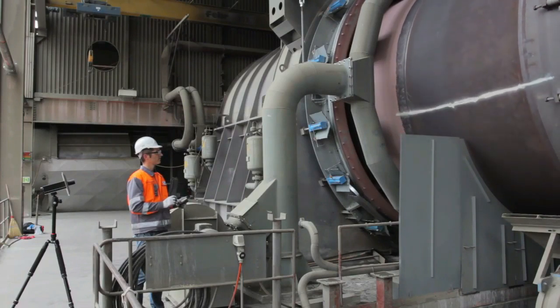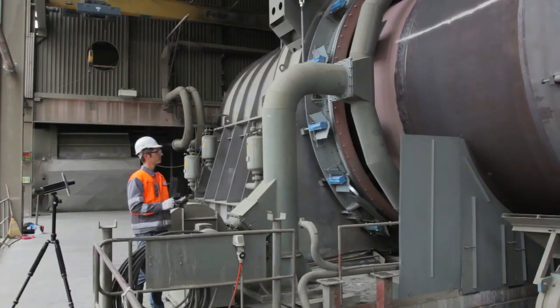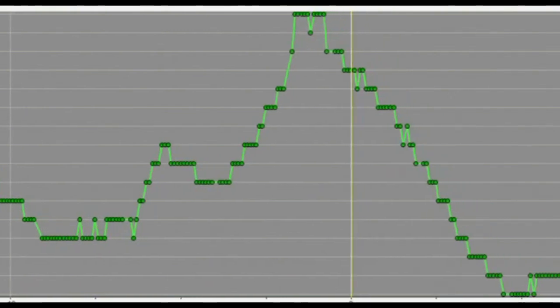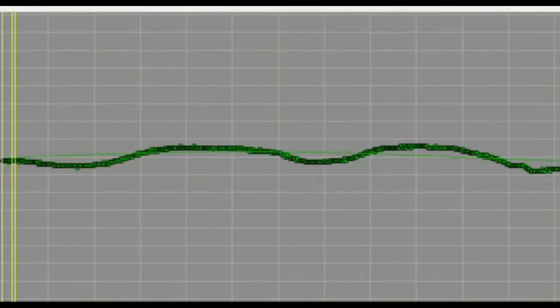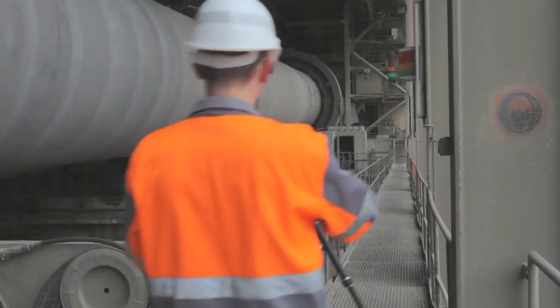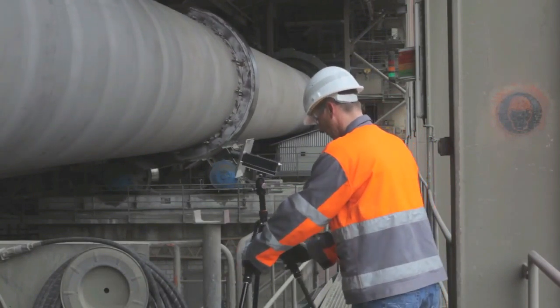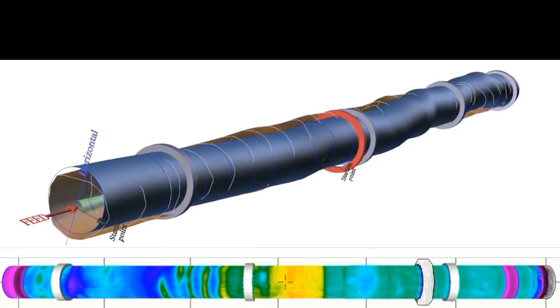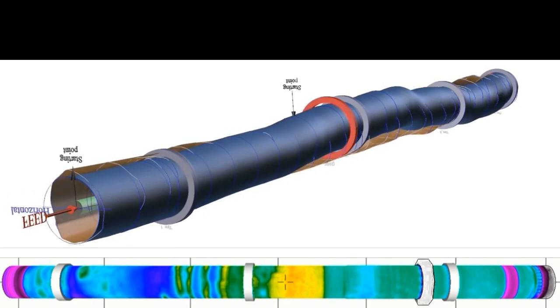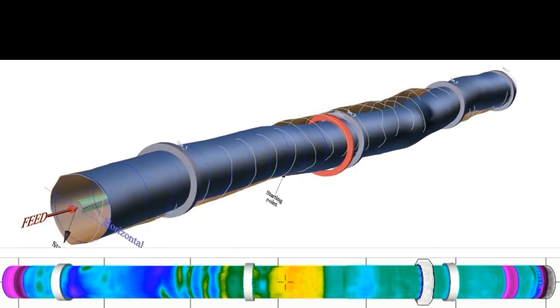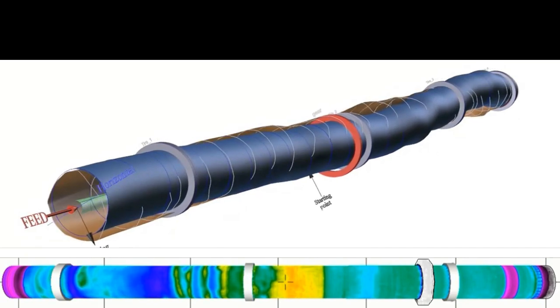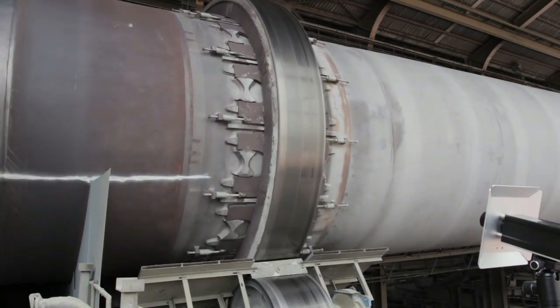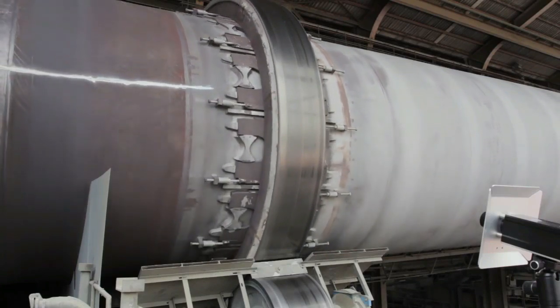To measure the shape of the shell, the kiln shell laser is placed along the rotating kiln and continuously measures the distance to the shell surface. Deformations for each measured position are generated and appear as a graph. Several measurements along the kiln can be combined into a full three-dimensional graph, showing the severity of deformations in different colors — a great help to identify areas where special attention to the refractory is required. In case of reduced refractory lifetime due to shell deformation, the sensor helps decide which shell sections need to be replaced.